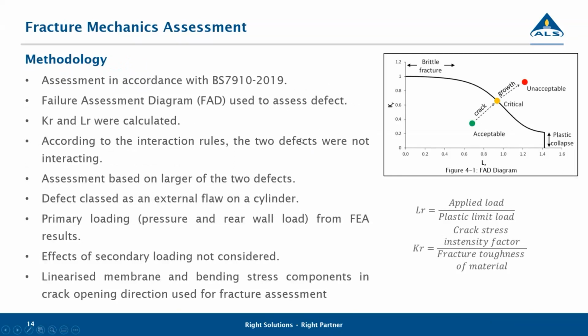So the next step we did is we also did a fracture assessment to see if it is plausible that the tube failed under design load conditions with that crack geometry. So we used the BS7910 approach, constructed a failure assessment diagram with a failure assessment curve. We calculated the toughness ratio and plastic collapse ratio on the Y and X-axis respectively. And we used one defect, the largest one, because the cracks, according to the crack interaction rules, were not interacting. So we based the assessment on the larger of the two defects. And we classed the defect as an external flaw on the cylinder. The primary loading considered was pressure and rear wall load. And we used the FEA model to get that loading from the bracket to do this assessment, which we'll talk about a little bit later.